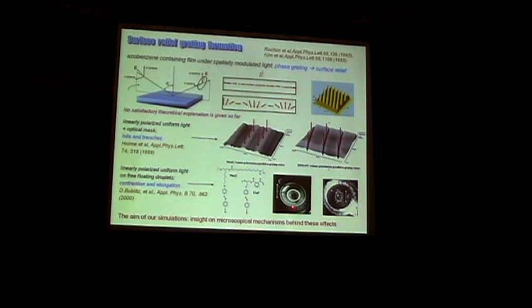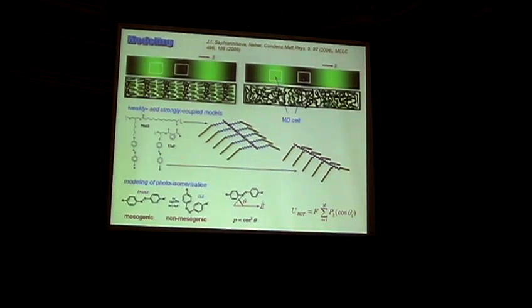Also, related experiments were made with free-floating films of azobenzene, and it was found that the film contracts along the polarization direction and extends perpendicular to the polarization. So our aim is to model such different photo-induced deformations depending on the structure and also to see whether we can see some microscopic mechanism behind these shapes.